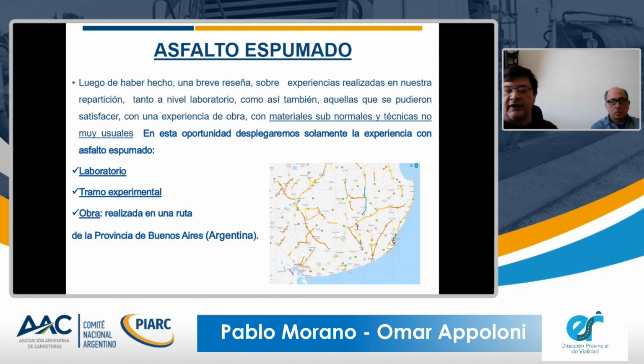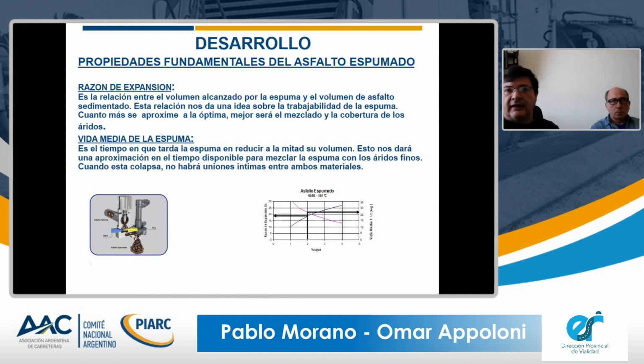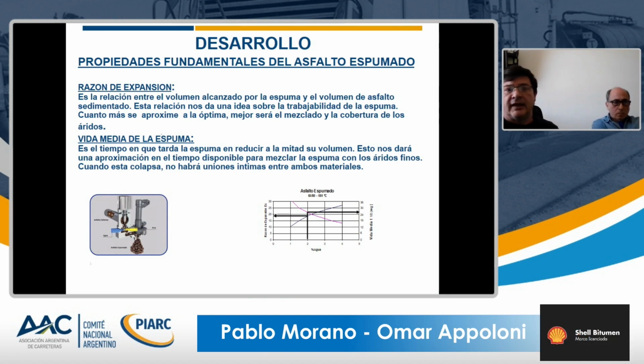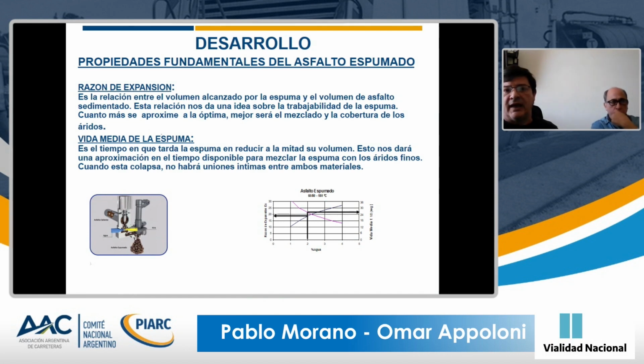First, as I said, we started with lab work and lab tests. As we know, foamed asphalt stabilization has 2 aspects: the expansion ratio, which is the relationship between the volume of the foam and the volume of the sedimented asphalt. This gives you an idea of the workability of the foam material, and we will always try to come as close as possible to the optimum ratio. The other is the useful life of the foam, which depends on the time this foamed asphalt takes to reduce its volume to half. The longer that, or the bigger that number is, the more time you have to use it in the mixes.